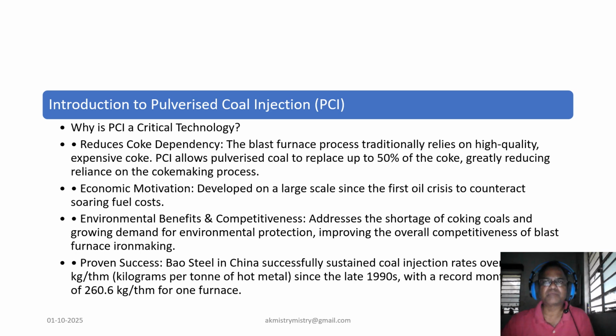Pulverized coal injection (PCI) is a cornerstone of modern iron making. Its primary purpose is to reduce blast furnace dependency on high quality, expensive coke by replacing up to 50% of the coke with more readily available pulverized coal. The PCI techniques significantly lessen the reliance on the coke making process.